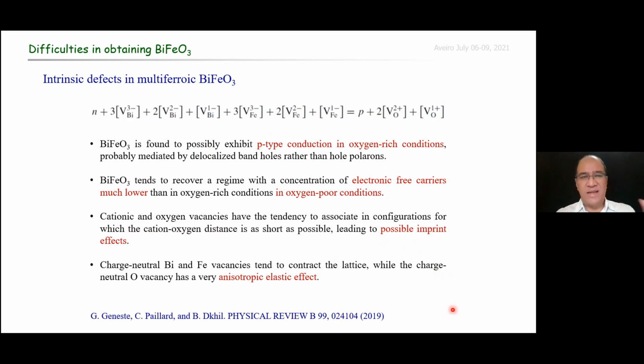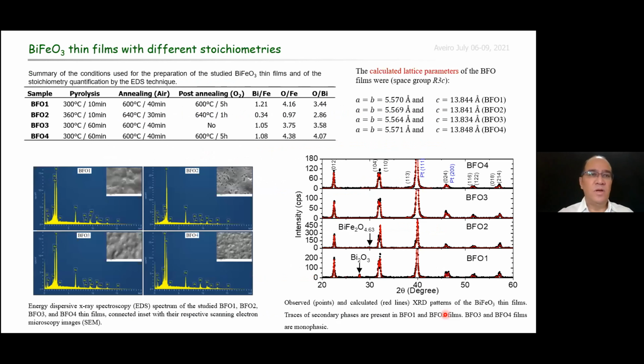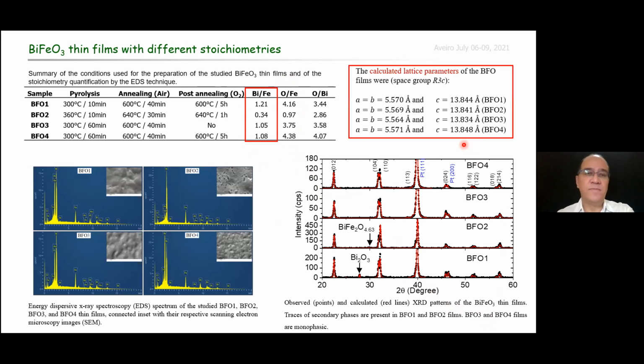In this complex scenario, we prepared a set of bismuth ferrite thin films with different stoichiometries to investigate the effects of different defects on their physical properties, focusing on the dielectric and electrical properties. This table summarizes the main conditions of the studied BFO thin films prepared by chemical solution deposition. The EDS technique was used to quantify the film's stoichiometry, while X-ray diffraction was used to study their structures.